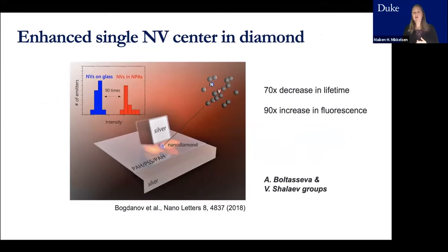So this is work done by Sasha Boltasseva and Vlad Shalaev, where they used nanodiamonds with embedded nitrogen vacancy centers. For single nitrogen vacancy centers, they could see a 70 times decrease in the lifetime and a 90 times increase in the fluorescence. So I think it's very exciting that these nanogap structures can indeed be useful in a number of systems.